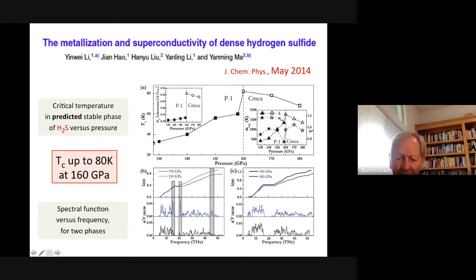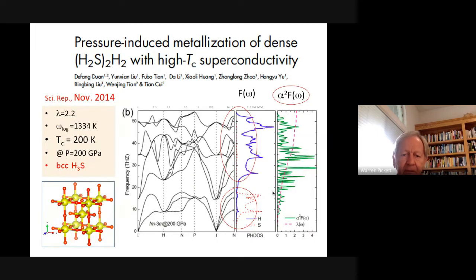And here's a curve. These are calculated numbers. The critical temperature versus pressure in this space group P1 bar, which is a very low symmetry space group. And then at 160 gigapascals, there's a structural transition from this structure to this one. And the calculated TC goes up to 80 Kelvin here and then decreases with more pressure. That's in H2S. I'll show one next slide, a little bit more.